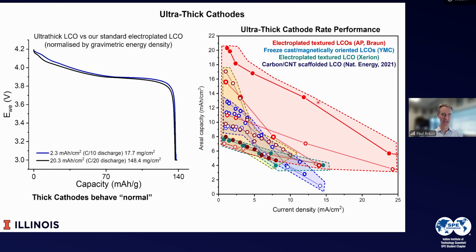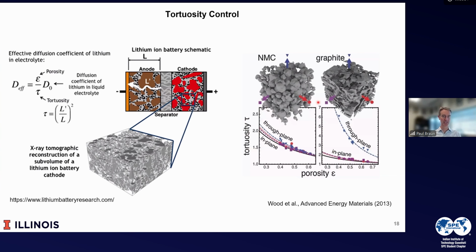So again, I think this shows the importance of orienting material in the vertical direction. And a major part of that is because of the reduction of tortuosity. Remember that when you pack a powder, it will tend to be quite tortuous. The tortuosity can be 2 or 3. In some cases, it can even be up above 7 or 8, for example, in graphite, because of the flake-like nature. And so this provides much better transport because the tortuosity is close to 1.